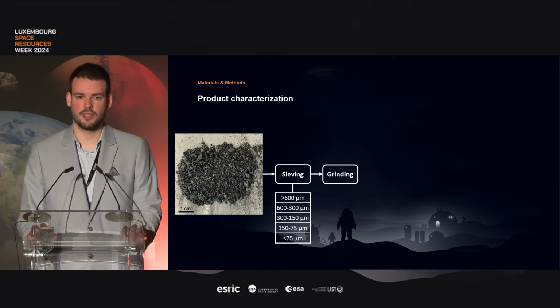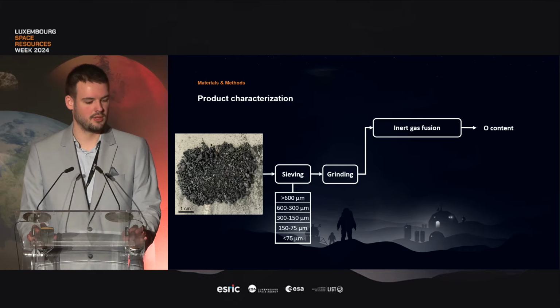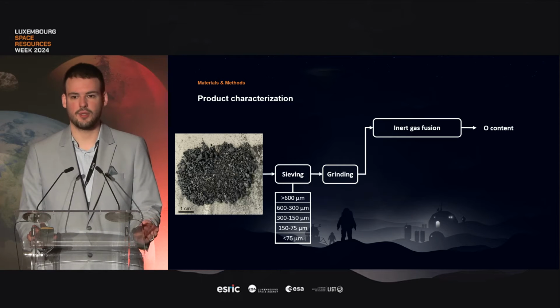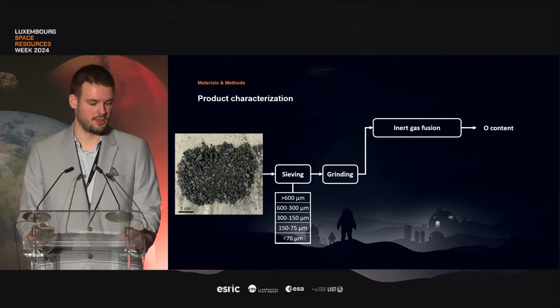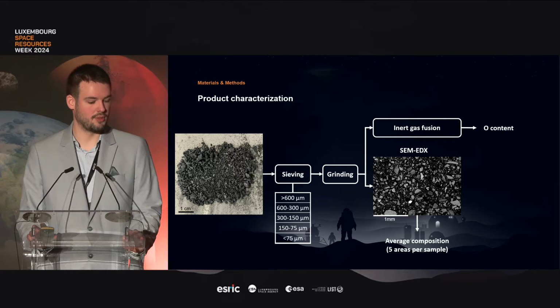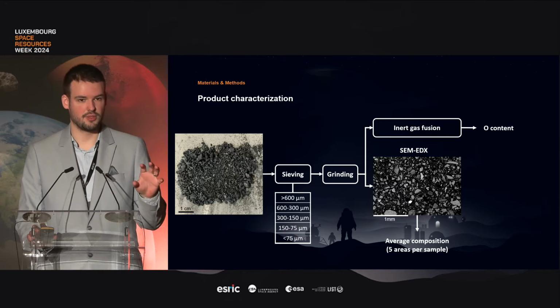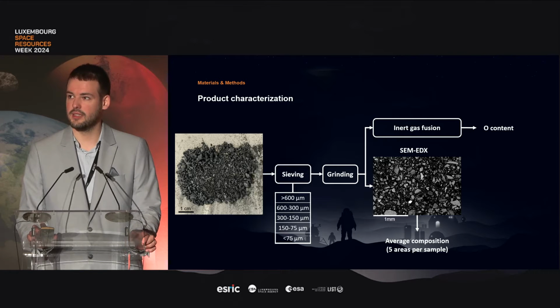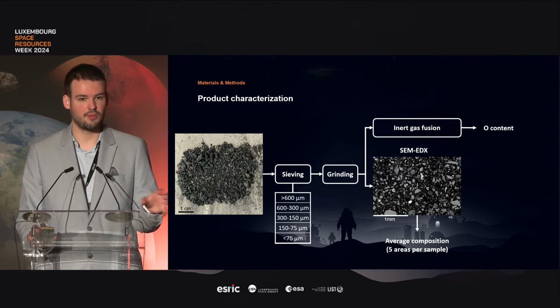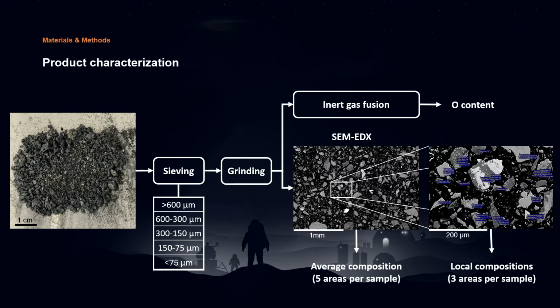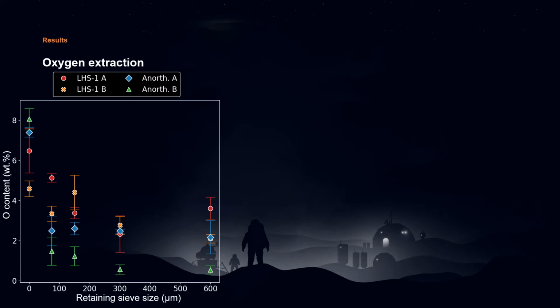And then I'm going to present today 2 different analyses, 2 different data streams. First of all, we characterized the oxygen content that's remaining in those materials through inert gas fusion. And then we looked at the composition of the metals. The composition, we obtained it from SEM EDX. And we did analysis of some large areas that you can see depicted here that give us an average composition across the area. And then we also zoomed in a bit and did some point-by-point analysis of different particles.